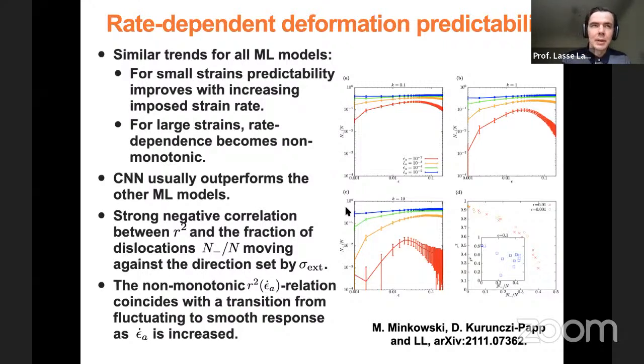However, if you have a smaller strain rate, then the interactions between dislocations are very important. And what happens is these dislocations form complex multipolar structures, which tend to drift slowly together as you apply stresses. These structures contain both positive and negative dislocations. So there are lots of dislocations that move against the direction set by the external stress when the strain rate is small. What we can do here is measure this fraction of dislocations moving against the external stress, so n minus divided by n, as a function of strain for different strain rates